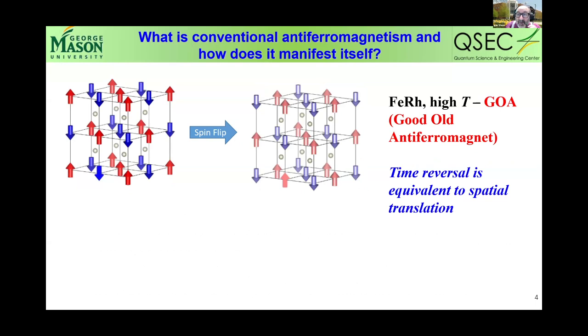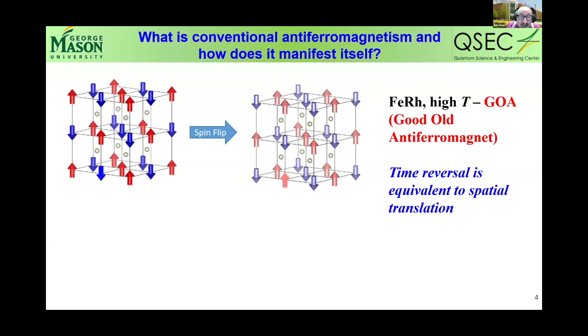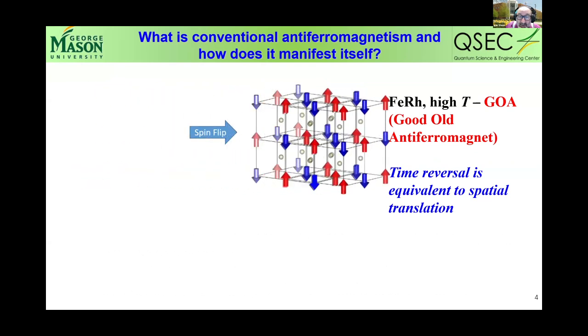So now what is a conventional antiferromagnet? Specifically, this example is of iron rhodium in its high temperature phase. It's an interesting material which has both ferro and antiferro phases, depending on the temperature. Basically, spin flip is equivalent to a spatial shift, a spatial translation. That is to say that it's essentially the same material when you flip spin.